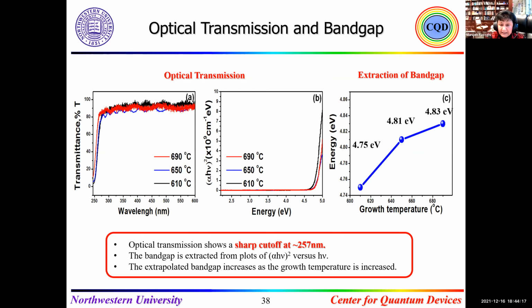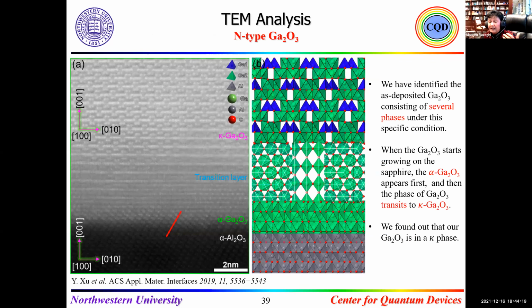But we immediately used transmission electron microscopy to get ideas about the symmetry, because symmetry is very important. Interestingly, at Northwestern, Professor Dravid's group showed that when growing on sapphire substrate, first we have alpha gallium oxide, and after that it becomes kappa gallium oxide - that's what they published, and the paper publication information is there.